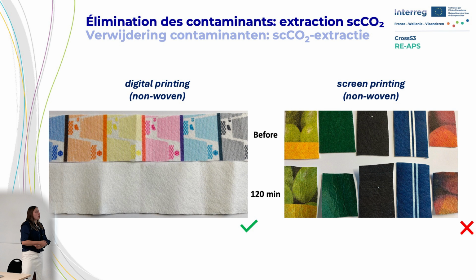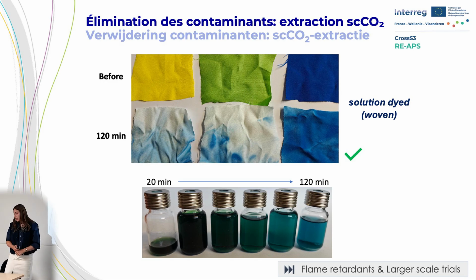The removal of the color was almost 100% effective. Then we went on with a screen-printed non-woven textile. Here we saw that the removal didn't change anything after 2 hours. The material even took up quite some extract, as you will see in the next slide. There we have the extracts, and for the first extract that we tried to take after 20 minutes, there was not a lot of extract, so it was all in the material. So until now, digitally printed materials seem to be effectively de-inked with ethanol as co-solvent, but for screen printing, ethanol seems ineffective. Then we had one last material that I tested.